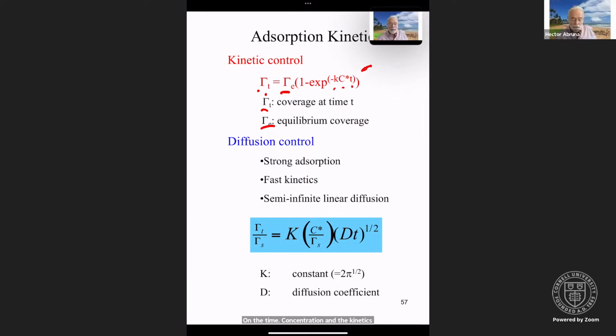On the other hand, if you're looking at diffusion control, this is typically the case of strong adsorption, fast kinetics, quote unquote, semi-infinite linear diffusion. This comes from Fick's law of diffusion that we will talk about when we start talking about transport. But the expression is that gamma at some time t versus gamma of the equilibrium or saturation equals k, a constant which is a geometric factor, times concentration over gamma saturation, times the square root of Dt, where D is the diffusion coefficient. And so what this tells us is that with simple plots, we can tell whether a process is kinetically controlled or diffusion controlled.